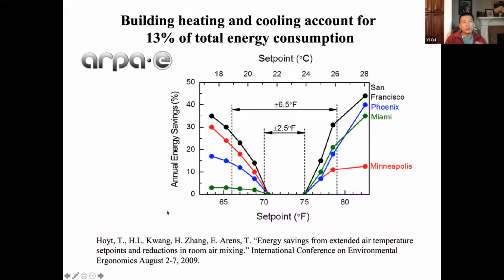I want to acknowledge that when we started this project, about 5 years ago, ARPA-E had the Delta program, started by Ping Liu. Ping is now a professor at UC San Diego with Renkun there. It's trying to solve the building energy consumption issue by changing the temperature set point in your building. Summertime, you can allow it to go higher. Wintertime, you can allow it to go lower. You expand the temperature zone people can live in. Every 1 degree Celsius set point change, you save about 10% of energy used in air conditioning in buildings. So 2 degrees Celsius is roughly 20 to 30%. So it's a lot of saving. That was the starting point when we started this project.